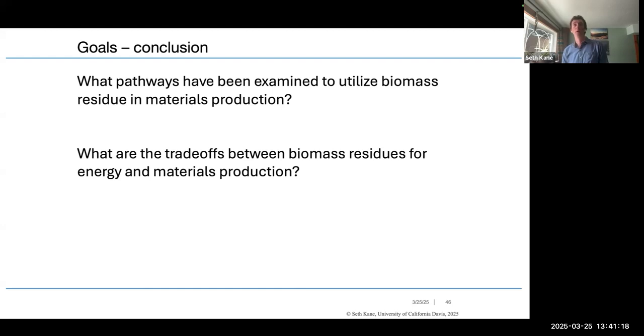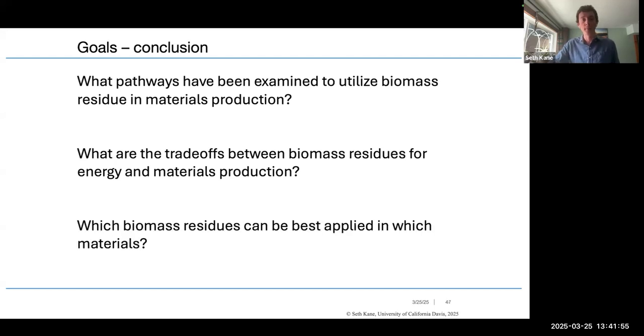For the trade-offs, we know that in our more oxygen present thermal conversion processes, we're going to be producing more bio-based energy, but less materials. And those materials might contain a lot less carbon because we've converted that to CO2 during producing energy, whereas our pyrolysis and gasification processes result in a higher carbon material that can potentially have greater benefits in materials production, but we're producing a lot less energy as a result of that carbon being stored. And so a trade-off there is going to depend on exactly what the emissions of your materials production and energy locally look like. And then finally, we've got which biomass residues can best be applied in which materials.